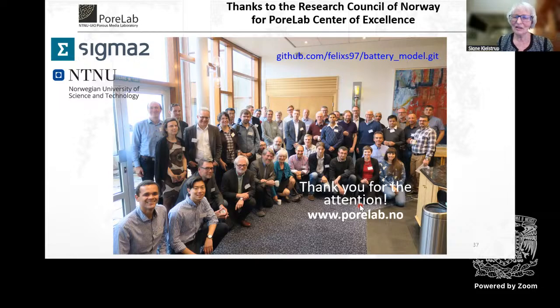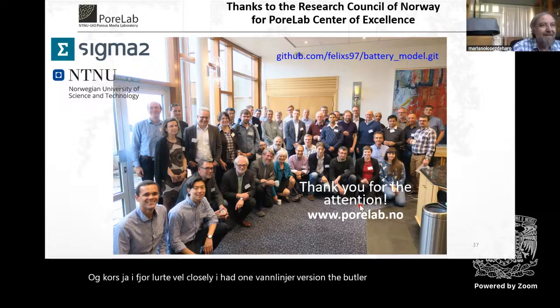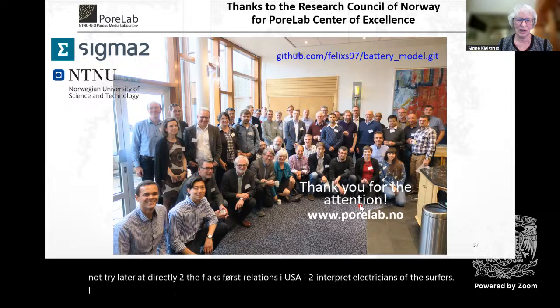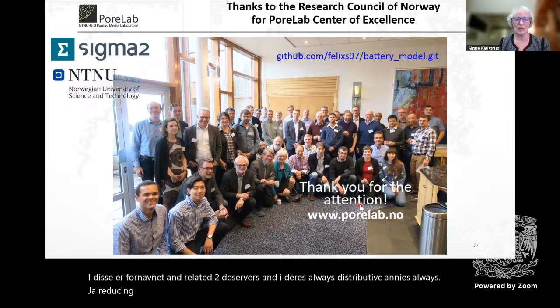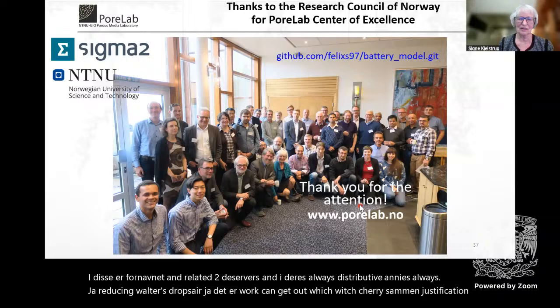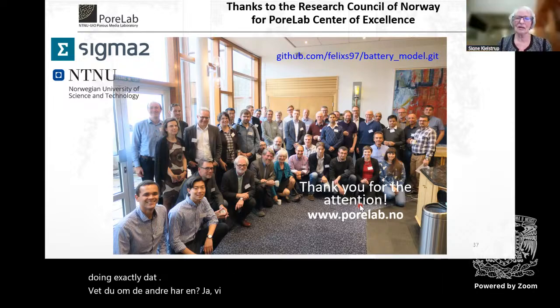Of course. If you look very closely, I had one nonlinear version, the Butler-Volmer equation. But I did not relate that directly to the flux-force relations. I used it to interpret the electric resistance of the surface. It is a phenomenon related to the surface, and it is always dissipative, and it is always reducing the voltage drop there, the work you can get out of it. So I think there is some justification for doing exactly that. But on the other hand, it seems to be sufficient with the linear version.